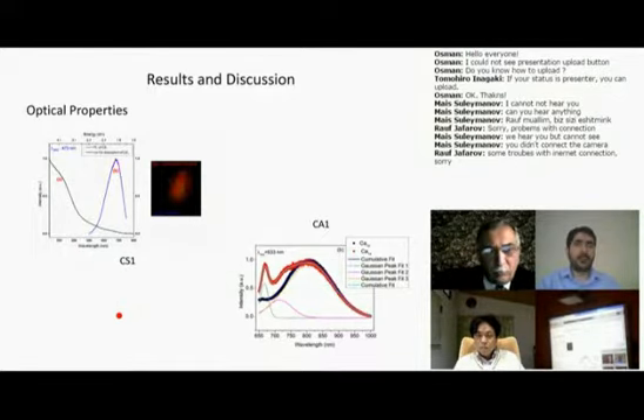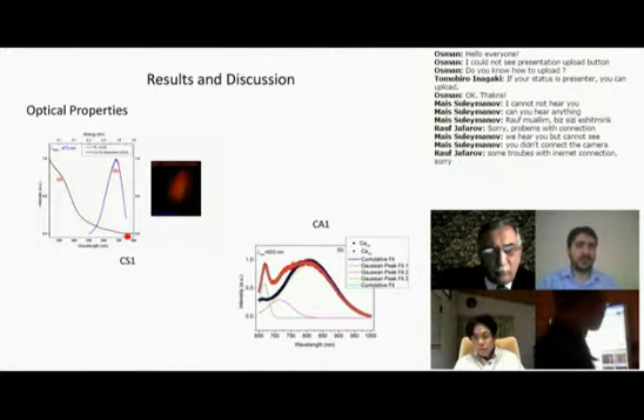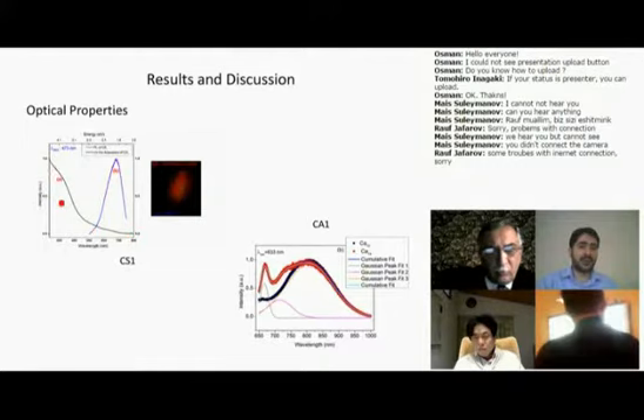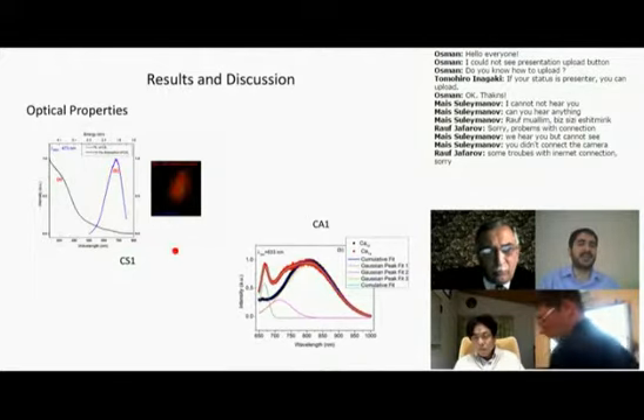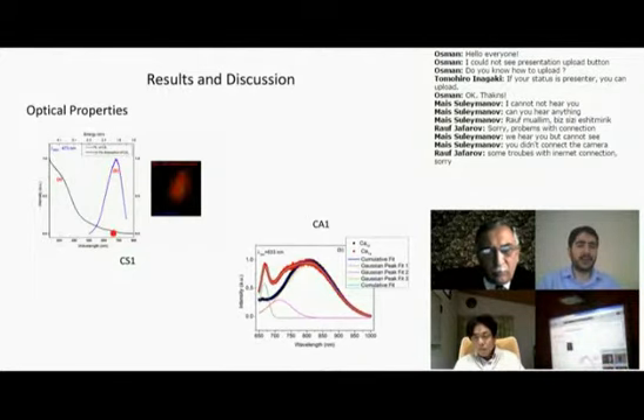Here are some optical analysis of our particles. What I did is I also took absorption spectra first. This is the absorption spectra of the first method, and this is the photoluminescence spectroscopy of our particle. It's around 700. I'm not sure whether you'll be able to read it or not, but yeah, it's around 700 nanometers.